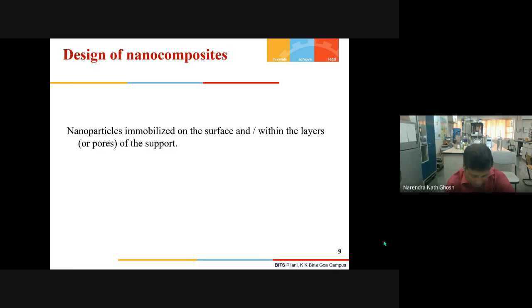Next, please. As you have observed in the materials we have designed, what have we done? We have taken a support, either a high surface area material like RGO, MXene, or porous carbon, and on the surface or within the layers of this porous support, we have incorporated the nanoparticles. There is a reason behind this strategy.